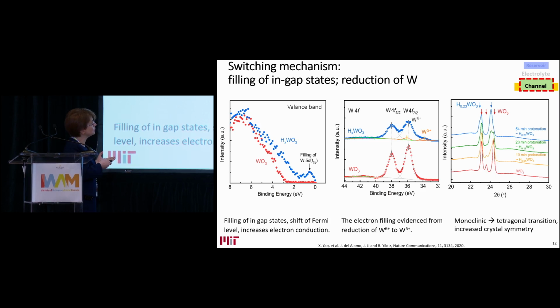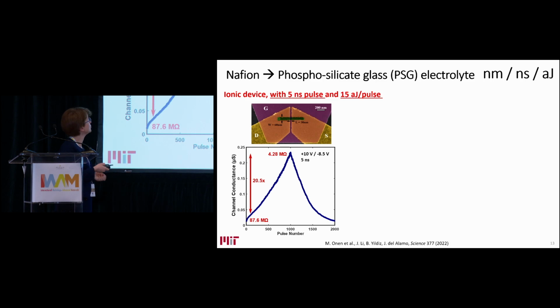But again, going back to tungsten oxide, as I showed theoretically at the beginning, the conductance modulation is by donating electrons that are brought with the proton to in-gap states. And you can see from the valence band comparison of the hydrogen-free tungsten oxide and hydrogenated or protonated tungsten oxide, we see the filling of these in-gap states associated with tungsten 5d t2g states. You can also see it in the tungsten oxidation state decrease from only 6+ to 6+ and 5+. And as we increase the hydrogen content, there is also an increase in the symmetry that contributes to increased mobility. So pretty much hydrogen serving as an n-type dopant that we are electrochemically controlling.